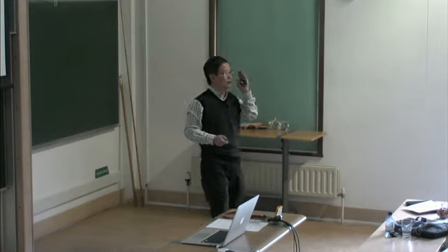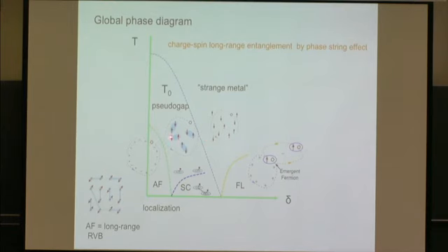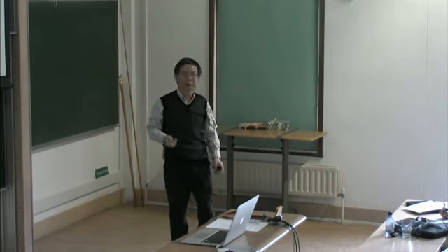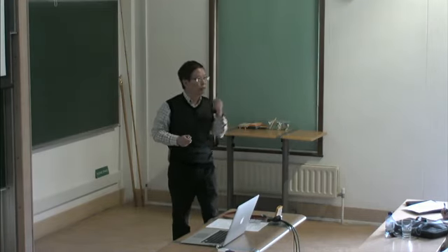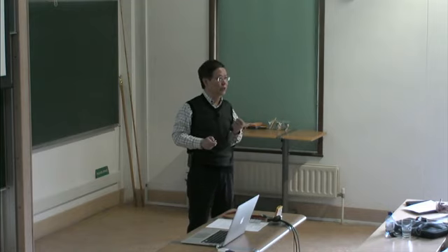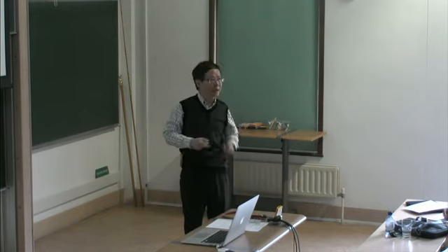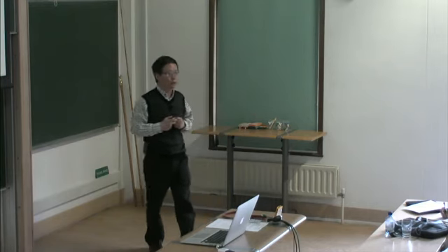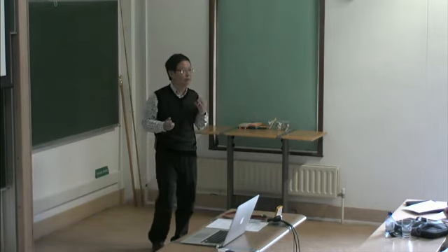And if you increase doping further, eventually this short-range RVB will be totally destroyed, such that you have a lot of free, localized spins there. So you have a lot of entropy in principle, and the hole will get strongly fluctuating. This is the maximal possible fluctuation. Instead of a localized hole, it actually makes a diffusive behavior. That's the strange metal behavior.